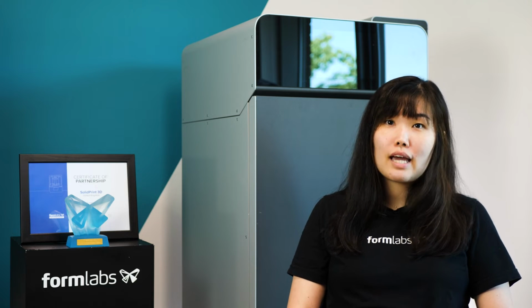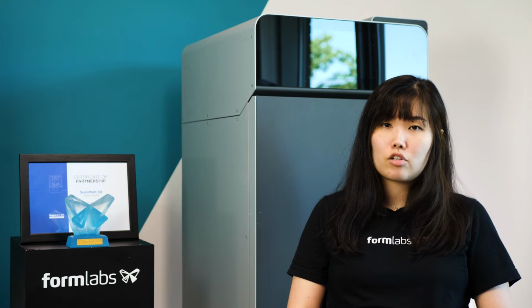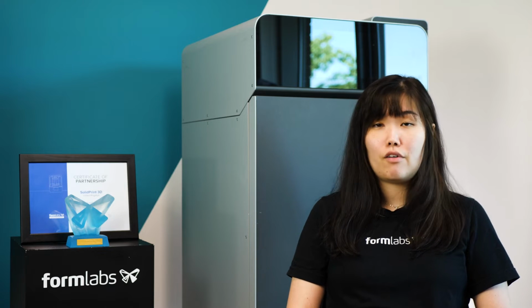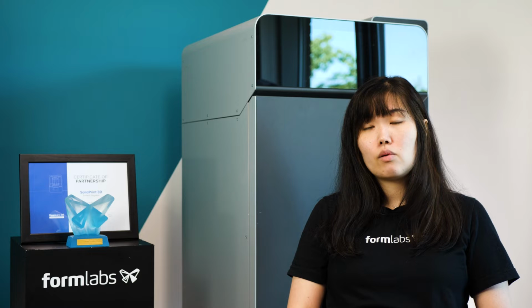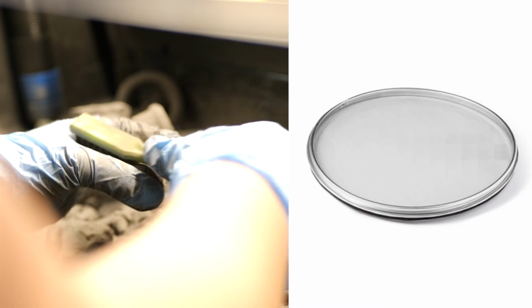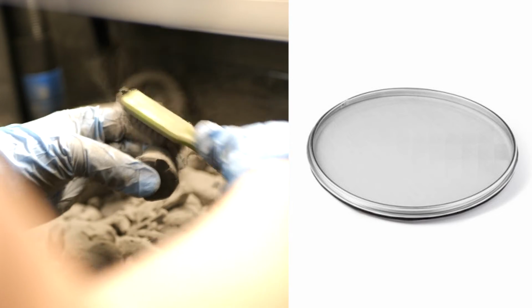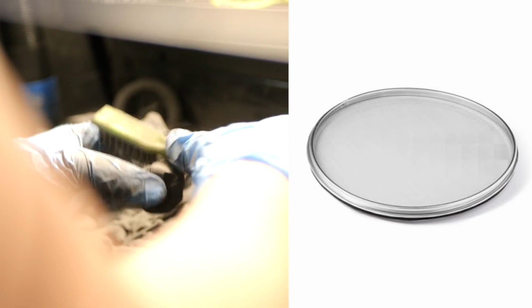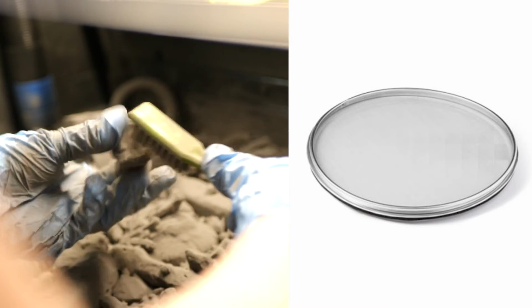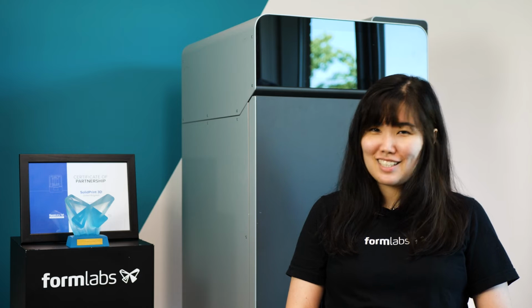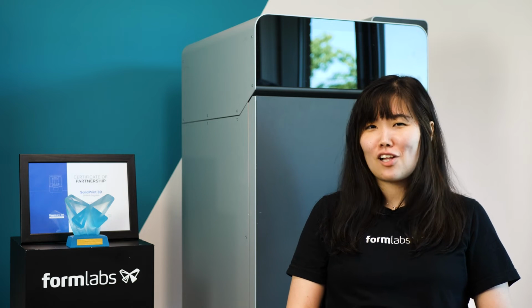So for those using FDM, you may be familiar with anisotropic properties, where mechanical properties differ based on direction. Similarly, with our carbon fiber, X, Y, and Z directions, mechanical properties do differ, so you might want to take that into consideration if you're orienting your parts to print in Nylon 11 carbon fiber. On top of that, as I mentioned before, carbon fiber particles are mixed with Nylon 11, so the sieve used in the post-processing station does need to be changed to a sieve 300. If that doesn't make any sense, don't worry, you can always reach out to Solid Print for more questions.